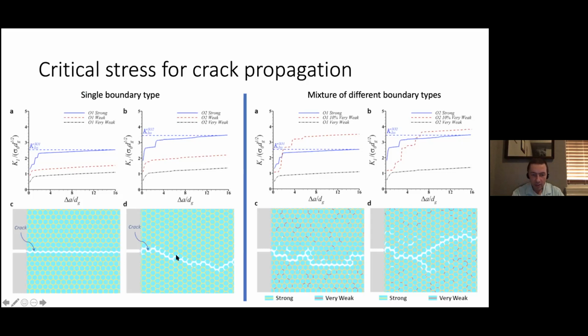So in addition to these visualizations that you see here of how the cracks are propagating, we can also plot out some quantitative information. All these plots above are showing you stress intensity. So basically it's a stress intensity as a function of the model geometry as well as the applied stresses, the stresses that have been applied in the far field. And this stress intensity tells us about how easy it is for the crack to propagate. You can think of a plot of stress intensity versus the crack length as a kind of equivalent of a stress strain curve in the case of fracture.